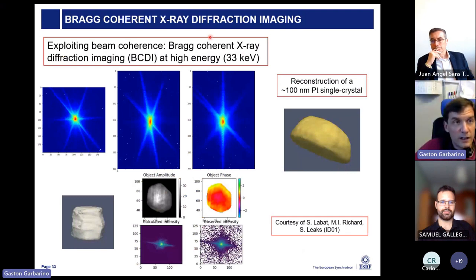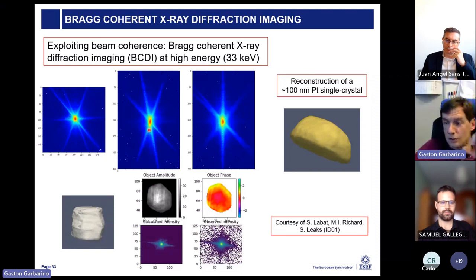At the same time, now exploiting the new capabilities in terms of coherence of the X-ray beam, we are able to, for example, illuminate this 100 nanometers platinum single crystals. And now, as you reduce the size of your nanoparticles, the Bragg spot of this single crystal will not be a nice Bragg spot, but at the same time you will have some fringes of interference around it due to the fact that you reduce the dimension of the nanoparticle. So if you are able to follow and really see how this reflection of this Bragg peak is in terms of angle, you can have a full reconstruction of your nanoparticle, and you can reconstruct not only the shape of the nanoparticle, but also get the strain state.